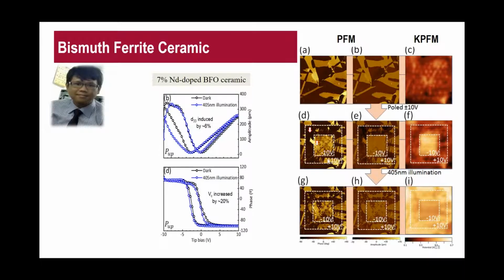On the left is the phase, showing the change of the polarization, and on the right is the amplitude image that shows the change in the strain or the material displacement, judging from the images we have seen here by applying a 10 volt bias. And how about providing light illumination? It also shows that it will affect the polarization as well as the strain behavior in the material. So PFM is able to detect the changes from the two external sources, that is the electric field as well as the light. And it is very obvious in KPFM in terms of illumination, compared to the one that has been applied with the plus minus 10 volt bias.